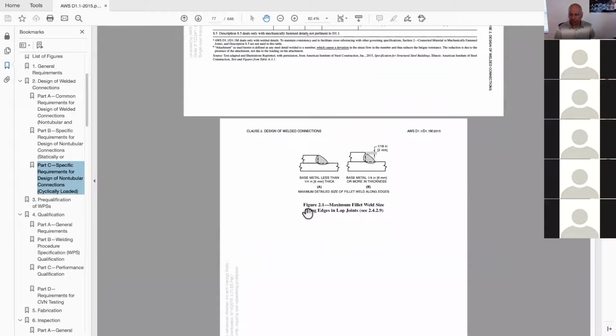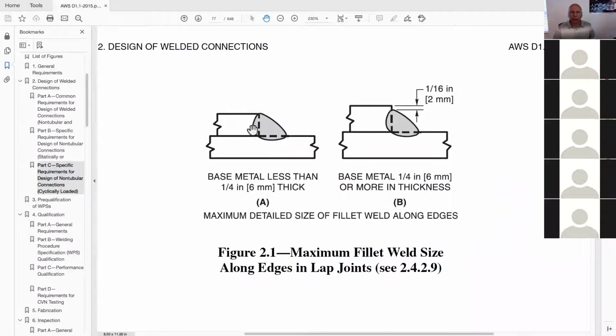If we look, this is a lap joint. The neck and the frame come together, and the welder put a weld in there. Instead of adding filler metal and creating a fillet weld throat that was adequate to transfer the load from the frame to the neck or the neck to the frame, the welder merely took the metal in the corner of the lap joint and melted it down. GTAW notoriously does not have deep penetration, especially on thin material where you have to weld with low amps. So if you melt this top edge and bring it down to the member it is lapping onto, you're just not going to get the weld throat that is required to transfer loads from the neck to the frame of the bicycle.